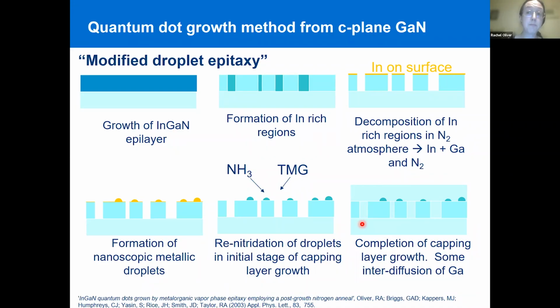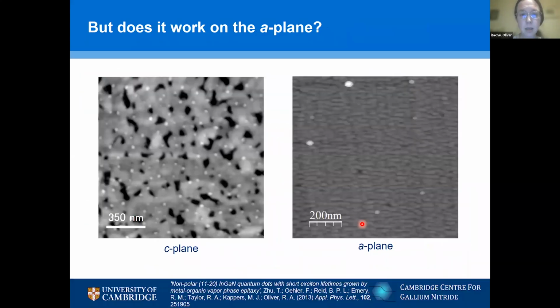Nonetheless, it gives really, really bright quantum dot emission. Pragmatically, it works really well. So this is the sort of structure we grow on the C-plane. This is prior to the nitridation step. So this is actually the metallic droplets we are looking at here.